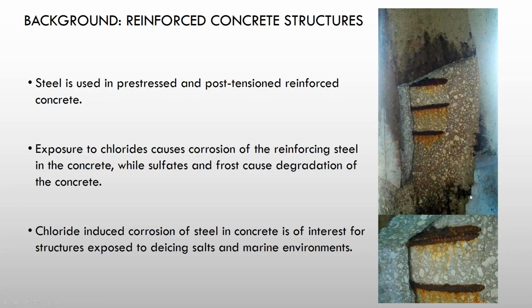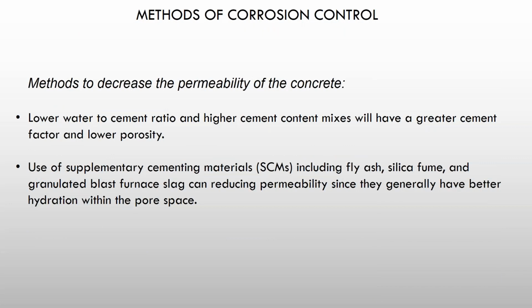A little background: steel is used in pre-stressed and post-tension reinforced concrete. Exposure to chlorides causes corrosion in the reinforcing steel in the concrete, while sulfates and frost cause degradation of the concrete. Chloride-induced corrosion in steel concrete is of interest to structures exposed to de-icing salts and marine environments. The methods to decrease the permeability of the concrete are to use a lower water-to-cement ratio and higher cement content mixes that will have a greater cement factor and lower porosity. Use of SCMs, including fly ash, silica fume, and granulated blast furnace slag, can reduce permeability since they generally have better hydration within the pore space.